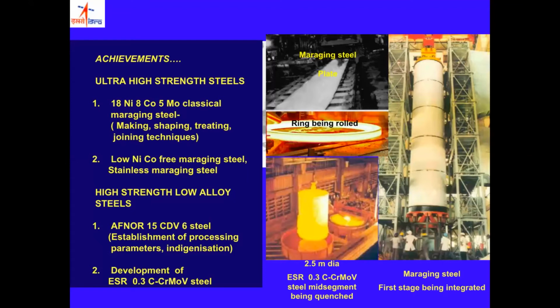On the top, you are seeing the plate, which is being rolled at Rourkela Steel Plant, Rourkela. And then this is the motor case. These are the various segments of the motor case. This has 5 segments, which have been made out of this ultra high strength maraging steel. And we are also working using 15CDV6, that is called high strength low alloy steel, HSLA. And for that, heat treatment is very critical. Such a big size of motor case has to be heat treated. So this is the heat treatment facility which has been established for this special steel.